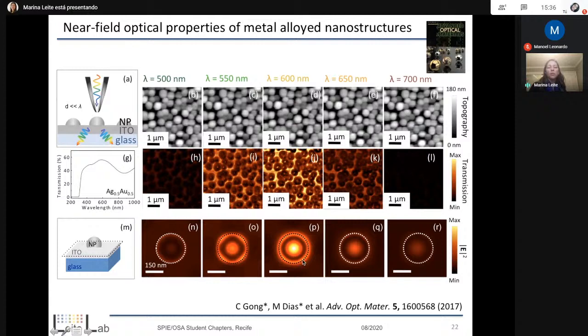So just be aware that the monitor is actually in the ITO layer. So really at the interface of the metallic particles, and around them, we have this bright field and underneath those. And this really is a characteristic of the localized surface plasmon resonance and an enhancement in our electric field. You can see here in the simulations, our scale is the modulus squared of the electric field. So that's something that was really neat for us.